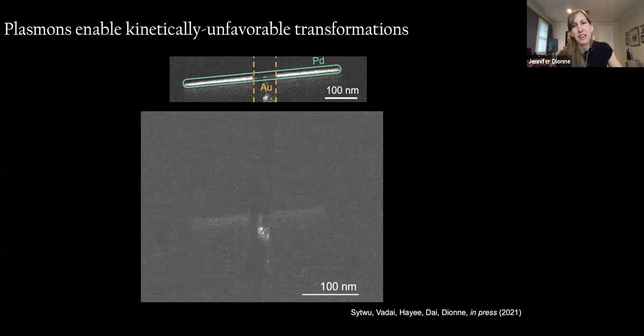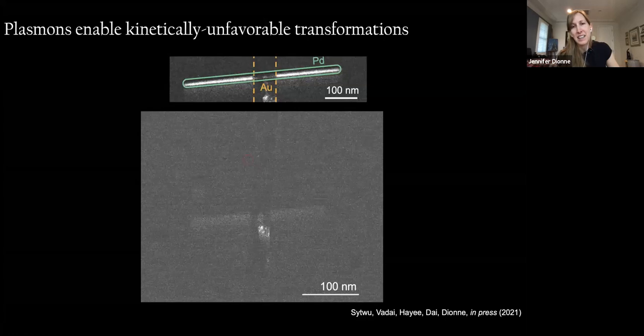And then once we turn the light off and we increase the pressure, we can get the system to hydrogenate again. You'll get to see the contrast in just a few seconds, where now you can see the hydrogenation is again occurring from the tips of the nanoparticle.